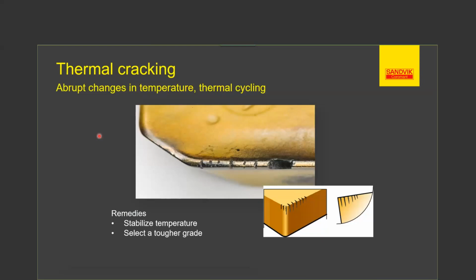And again, sometimes what happens is we push the inserts to failure, and we have a whole edge line that is actually gone, and we think we might have microchipping, or we think we might have edge line failure. The fact is, what's happened is we're actually getting thermal cracking or comb cracking. So again, we need to stop the inserts prior to complete failure, read the wear, and make the adjustments accordingly.